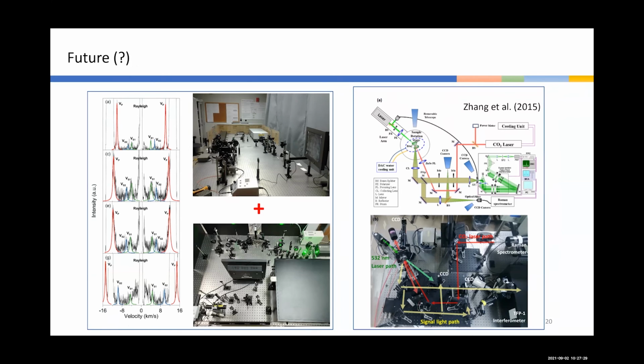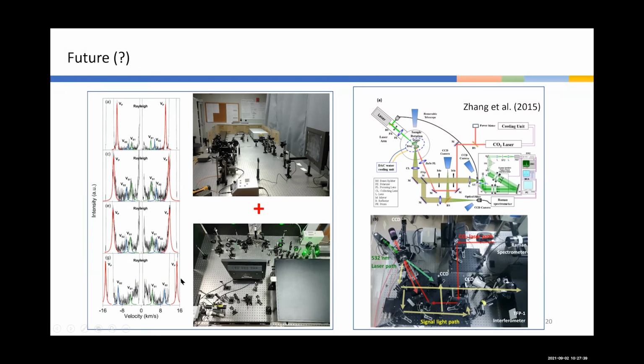In this case, we cannot use Brillouin scattering to resolve the single crystal elasticity for most of the mantle minerals above 25 GPa. The good thing about ice is that its signal is very strong. So when the VP of the ice is faster than the diamond VS, we can see this VP peak again, shown by panel G on your left. But for most of the mantle minerals, we cannot do it at all because the signal is very weak. So how do we overcome this problem?